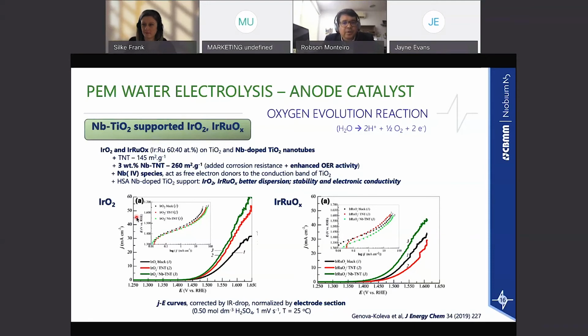This example comes from the literature. What people are trying is to support iridium and iridium ruthenium oxide, also using ruthenium, on a niobium-doped titanium support. It's amazing that niobium and titanium go very well together in hydrogen technology. It works for electrolyzers, but also for fuel cells. We'll talk about this a little later. This example is doped titanium, and the titanium was also nanostructured as a titanium nanotube. One of the reasons is that the niobium doping increased the surface area of the support remarkably, and this high surface area was able not only to better disperse and utilize iridium, but also to add more corrosion resistance to the material, make it more stable, and enhance the activity of the catalyst. Niobium is also a more reduced species, +4, which can increase the electronic conductivity of this material.